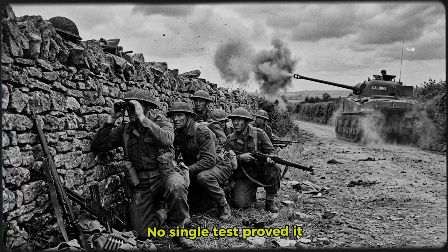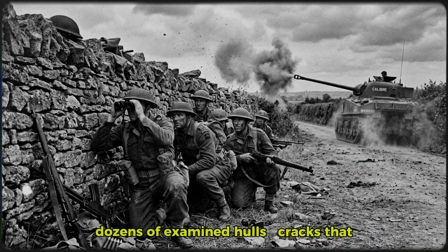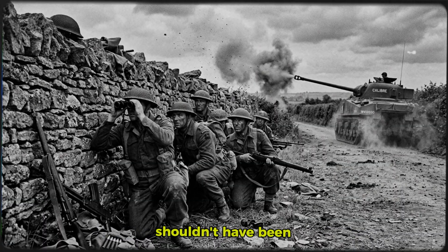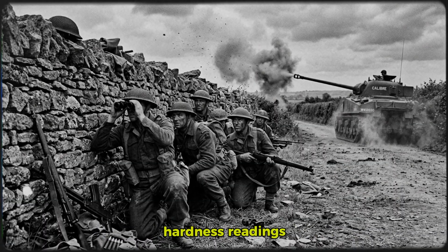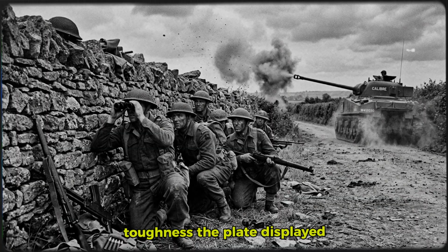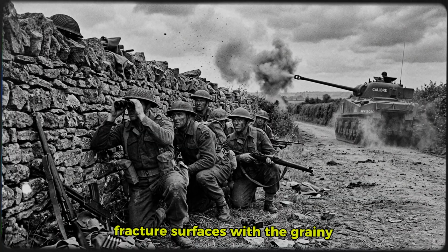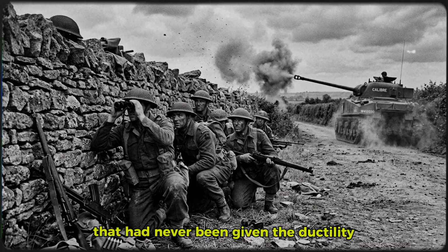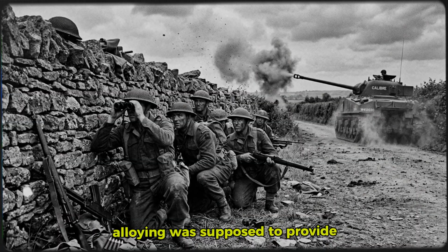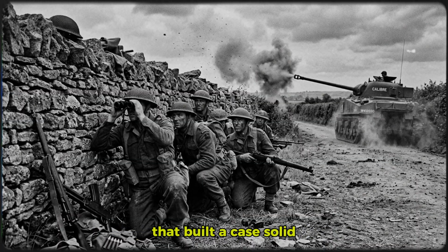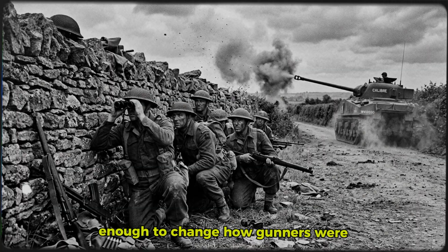No single test proved it. It was the pattern across dozens of examined hulls, cracks that shouldn't have been there in properly tempered steel, hardness readings that were too high relative to the toughness the plate displayed, fracture surfaces with the grainy, crystalline look of steel that had never been given the ductility alloying was supposed to provide. That built a case solid enough to change how gunners were trained to shoot.